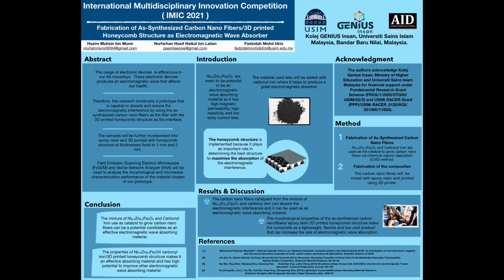Argon gas at 100 SCCM will be flushed into the closed furnace to eliminate air. The ethanol solution will be flowed for 30 minutes. After that, the furnace will be left to cool until room temperature. Finally, the samples can be used for the fabrication of the 3D printed honeycomb composite structure.